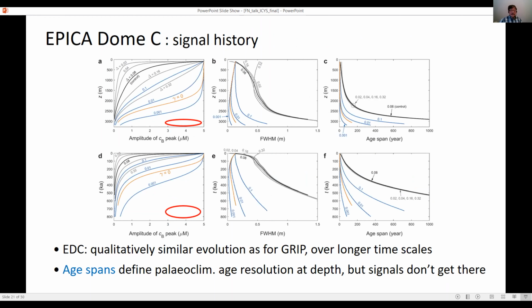The results for EDC are similar. These are just the same set of experiments run there. These age spans out here, these are the widths of signals in the time domain, could potentially define the resolution of paleoclimatic signals we can get from the EDC core at depth. I think Eric alluded to this idea, how well can we actually obtain information down there in terms of time resolution. And these runs could actually tell us a bit about that, except that signals don't survive in amplitude there, so we can't use these. If signals get there because of blocked veins, then we might use the blue curves. But as you can see, the age resolution becomes much better, even with blocked veins.